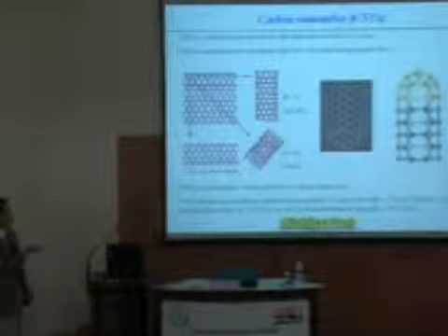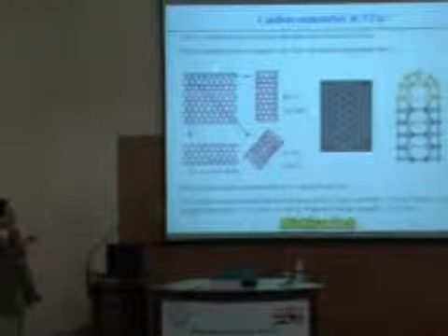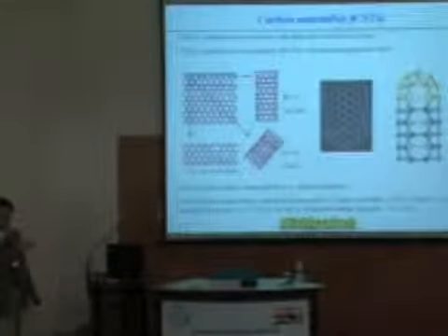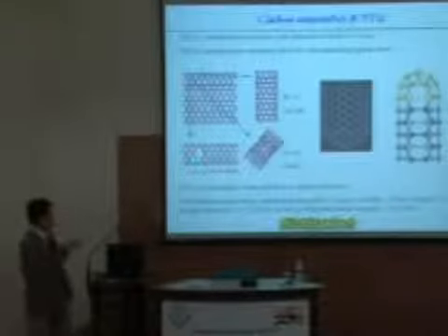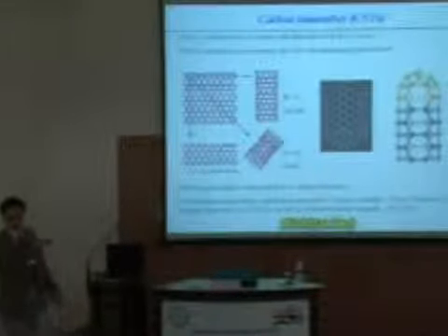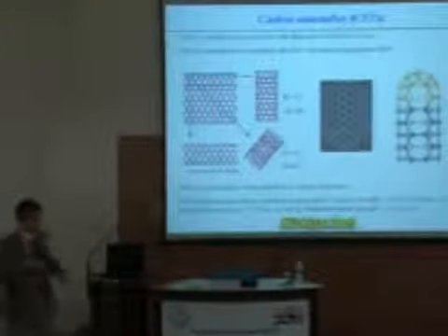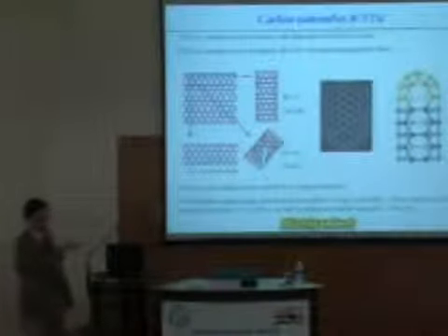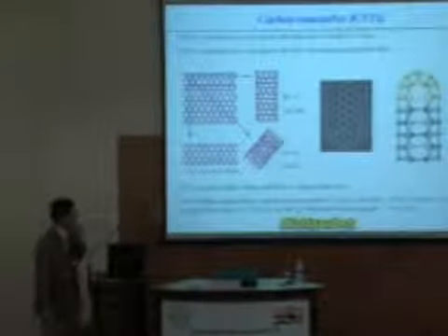In this case, you call this a zigzag carbon nanotube. Or you might want to fit these edges, which are in a zigzag shape, to match this edge by folding it downward. Then you can form this kind of nanotube called an armchair nanotube. Some of you already know that these nanotubes will always be metallic. They will conduct electrons just like a piece of graphite. And if you fold them in another direction, you form the so-called chiral nanotubes. They can be semiconducting or metallic as well.